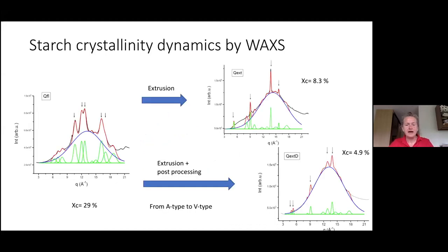And if we look closer at the starch crystallinity dynamics, we can understand from the study that the degree of crystallinity is changing. Here we have a crystallinity of exactly 29%. If we apply extrusion, we have a decrease in crystallinity, as is obvious from the decrease in the peaks, down to 8%. But if we dry this material, this food, we have an even further decrease and further shifts in the crystallinity of starch.